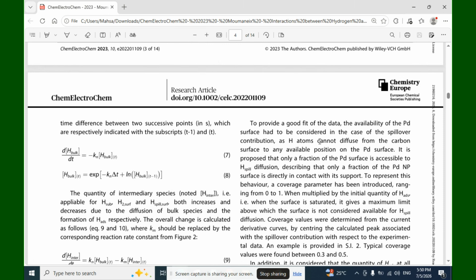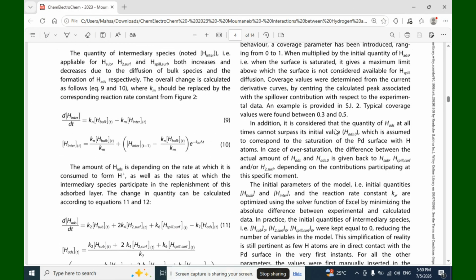Coverage values were determined from the current derivative curves by centering the calculated peak associated with the spillover contributions with respect to the experimental data. An example is provided in the figure. Typical coverage values were found between 0.3 and 0.5. In addition, it is considered that the quantity of hydrogen absorption at all times cannot surpass its initial value, which is assumed to correspond to the saturation of the palladium surface with hydrogen atoms.